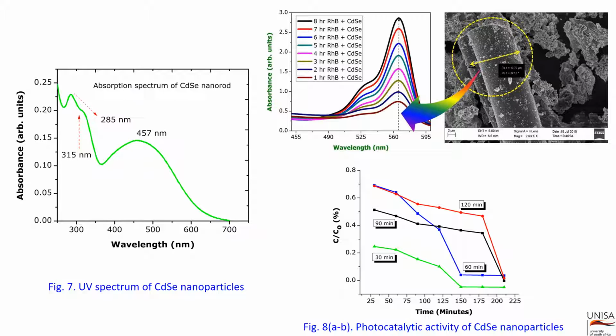In figure 7, the UV spectrum of cadmium selenide nanoparticles, there is a broad peak in the UV curve centered around 350 nanometer. As the cadmium selenide nanorods grow larger, the longer axes grow beyond the confinement regime and the excitation peak only depends upon the shorter axis of the rods. In this region, for the redshifting of the excitation peak, the spectral studies are carried out to detect the lower concentration of defects rather than optical observations, which is the mechanism where the impurity absorbs light, giving rise to a bound excited state, from which it returns to the ground state, in accordance with the color creation mechanism.